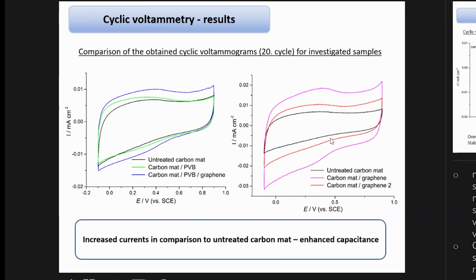Cyclic voltammetry results comparing the untreated carbon fiber mat covered with only polyvinyl butyral, and the carbon fiber mat with polyvinyl butyral and graphene nanoplatelets. As we may see here, the black diagram on the left has the smallest inside surface, and the other two have a greater surface between the lines of the graph. That means, as we calculate the capacitance as the integral of this surface, that our nano-modified coatings have better electrochemical properties.